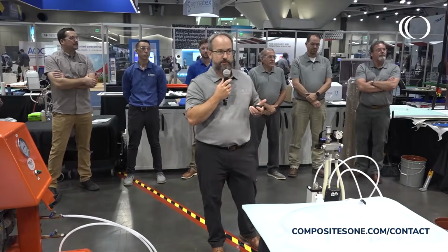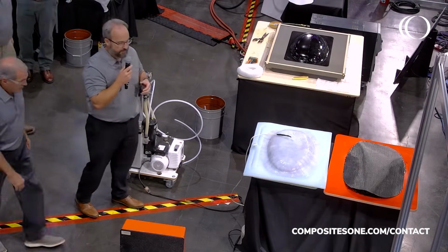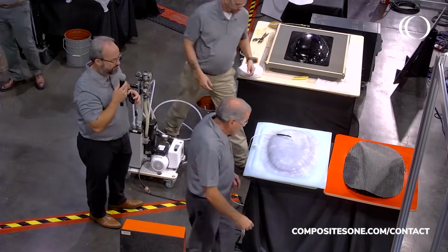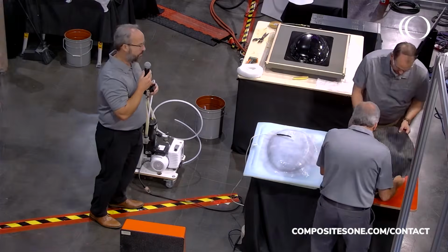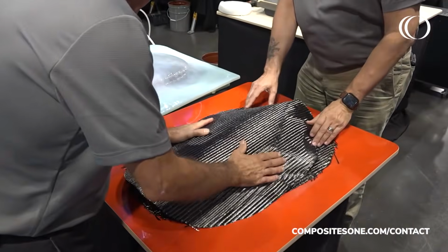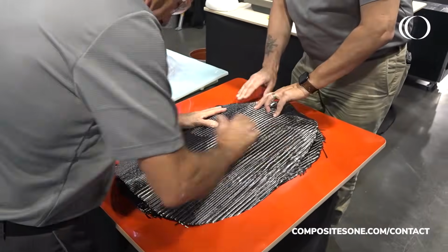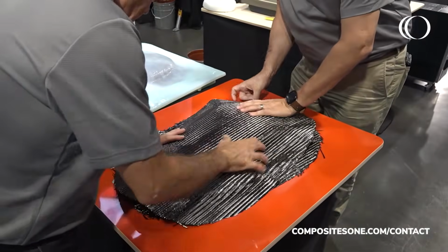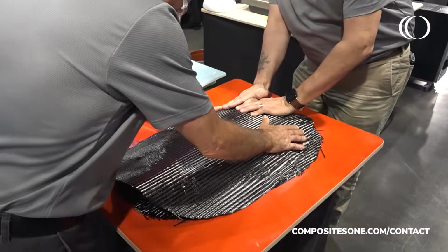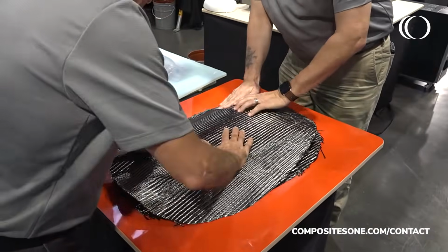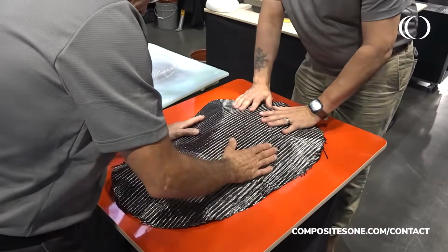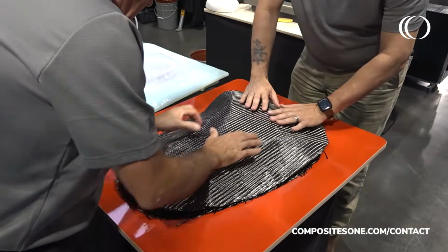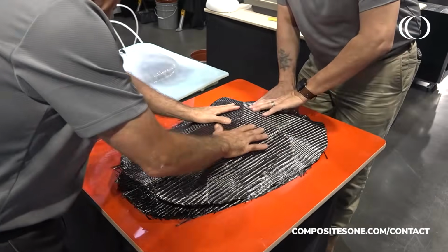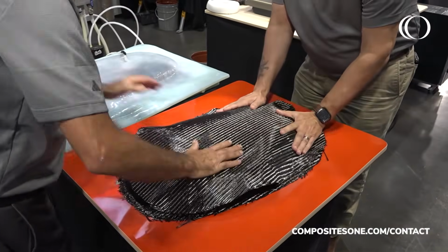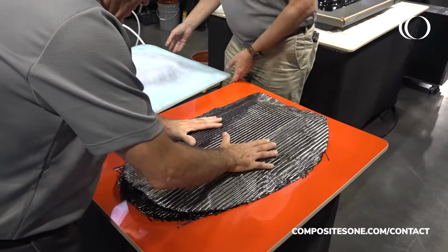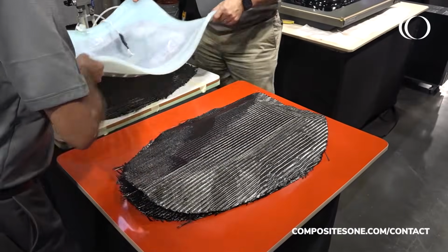So why are we interested in preforms? Basically, with preforms, we can precisely position the fabrics and fix them in place. We don't have to worry about any resin outlife, like if we were using prepregs, no working time issues if we're using liquid resins. The preform has a heat set binder. You'll learn a little bit more about that from Brandon. But it makes it very good to stabilize the fabric on vertical surfaces or even complex patterns. This dome shape we're doing, it looks fairly simple, but it's actually a pretty complex shape to conform a fabric to.